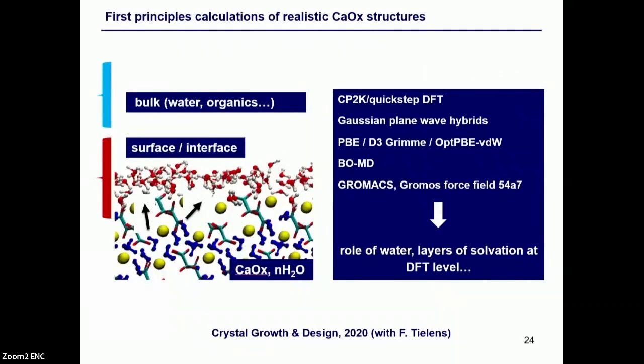Just to finish my talk, it's possible also to go to first principle calculations of what I call here realistic structure. What do I mean by realistic structure? Not only looking at the bulk of the hydrated calcium oxalate, but also at the interface. So playing with water molecules or organics, and also a bulk of a large number of water molecules and organics, let's say above the surface.